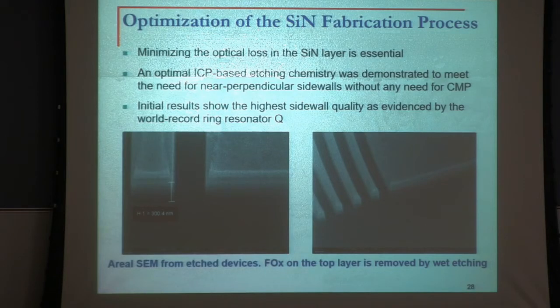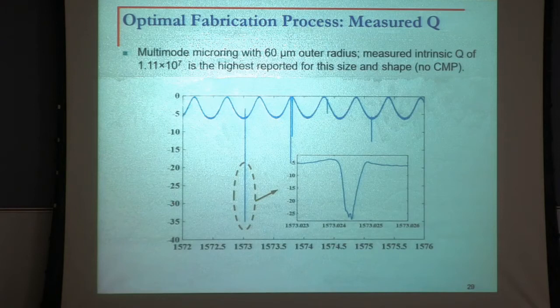We developed a very sophisticated, optimized silicon nitride process. Again, it took us probably about a year to optimize it. And now with that, we are able to get quality factors that we feel will be reaching more than 30 millions. This is the example sidewalls. And the material on the top is the flowable oxide, which can be removed. That's just like a mask, which will be removed at the end. But very good qualities have been achieved.